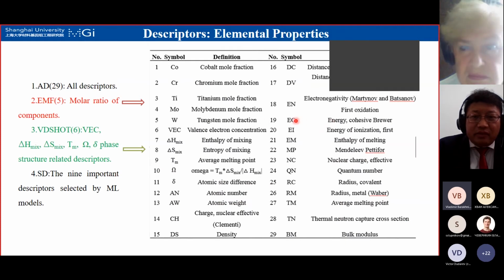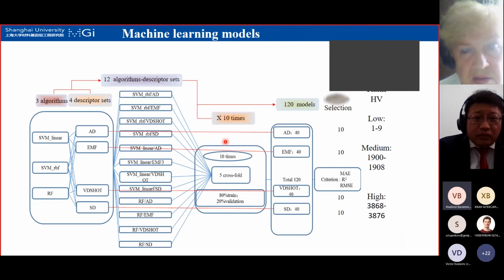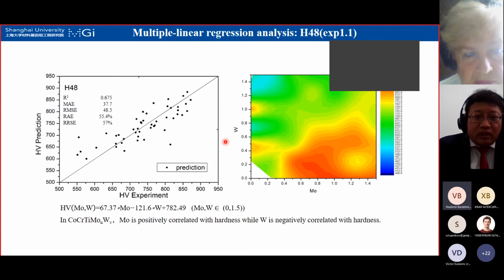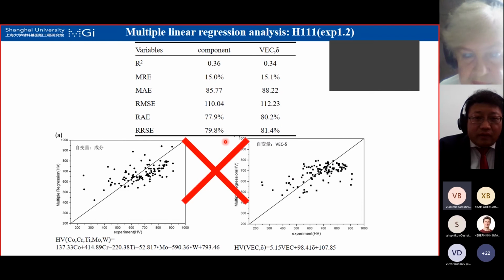Again, we start from these elemental properties, plus some compound features from the literature, like enthalpy of mixing or entropy of mixing, etc. Then we try several algorithms and several combinations of algorithm and descriptor, and we do 10 times training and generate 120 models, and then we take the statistical average to get the result. So this is just routine. If we did this by traditional linear regression, we would actually get contradictory results, which means machine learning is really necessary in this case.